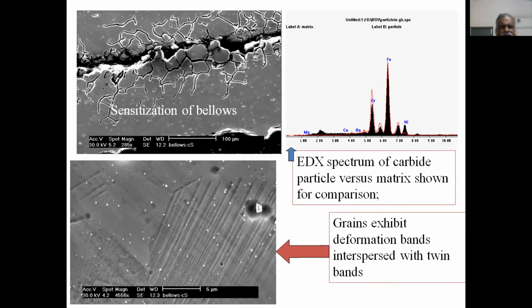And the sensitization causes a material to get corroded easily. And how is it sensitized? Sensitization is basically more chromium going into the grain boundary, forming chromium carbide, leading to depletion of chromium in the base matrix. And this results in attack of the grain boundary, and this is how it has happened.